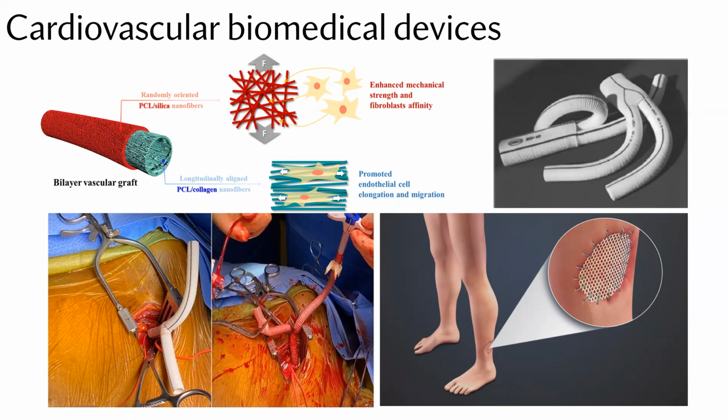Either we use processes like electrospinning or bulk fiber entanglements, and what happens is that they have directionality, so that allows the cells to sort of gain that initial shape and geometry due to the fiber organization. And then they also have a better mechanical strength because of this composite design. And then gradually the various tissue structures are going to form on the internal surfaces and the external surfaces, but usually the internal.